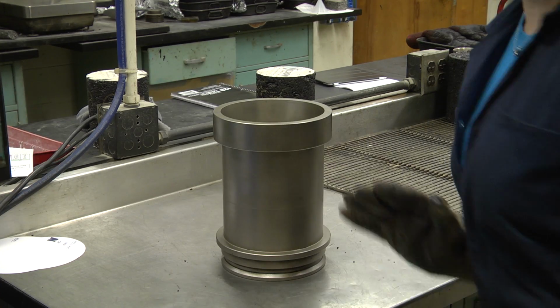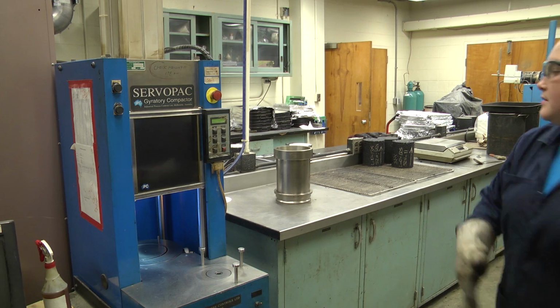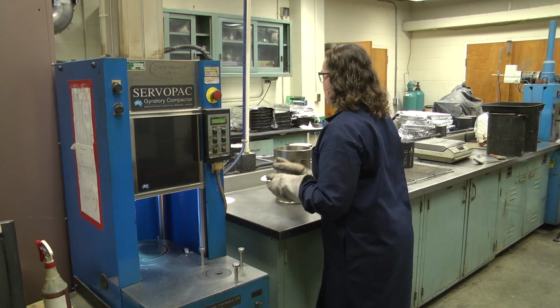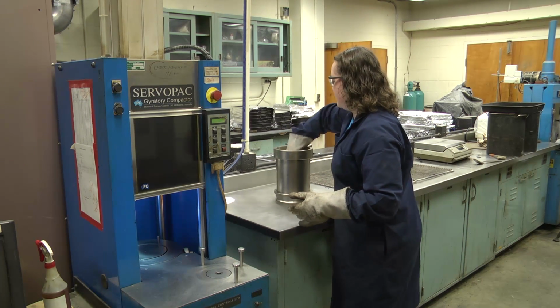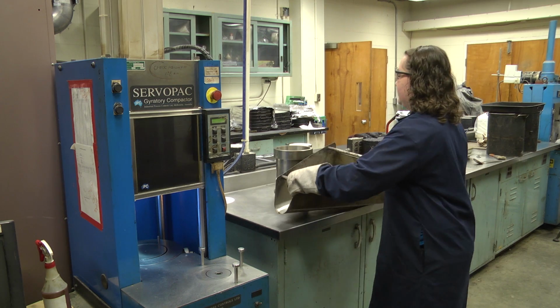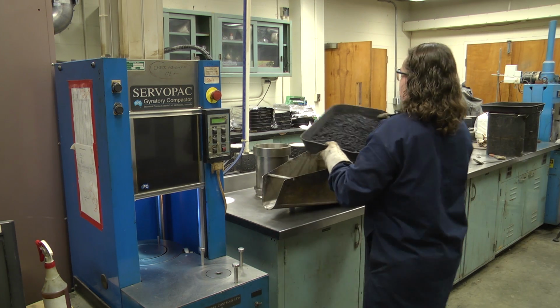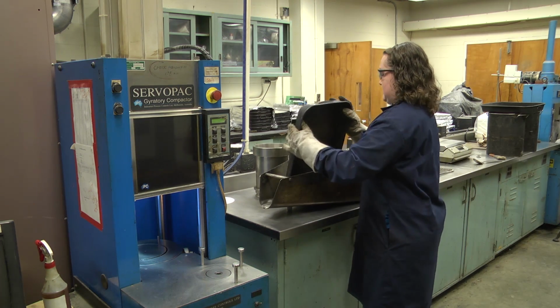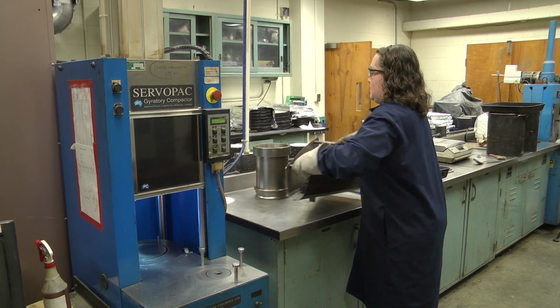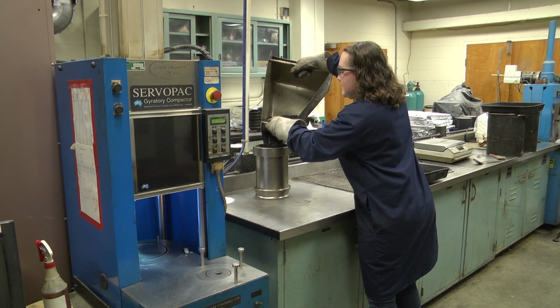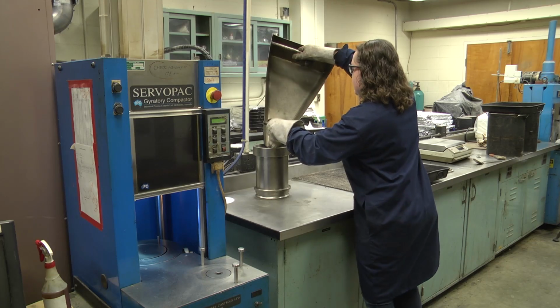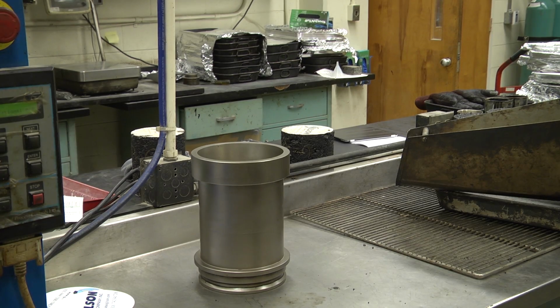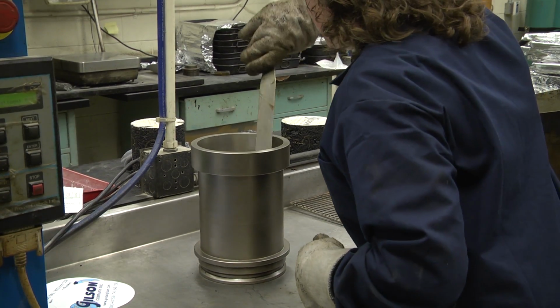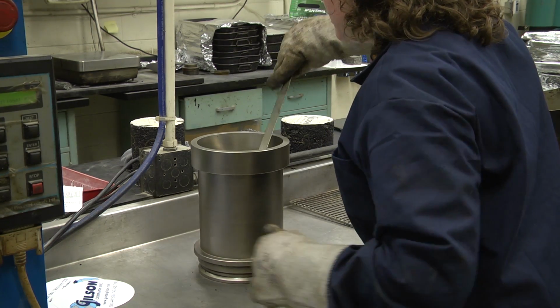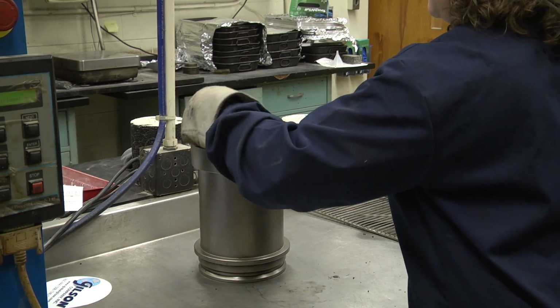Remove the gyratory mold and mold bottom from the oven. Place a paper disc into the bottom of the mold to prevent asphalt concrete from sticking to the mold bottom. Remove the funnel, followed by the loose mixture from the oven. Transfer the mixture into the gyratory mold using the funnel. Next, remove the spatula from the oven and use it to level the specimen. Place a paper disc on top of the specimen and place the end plate on top of the paper disc.